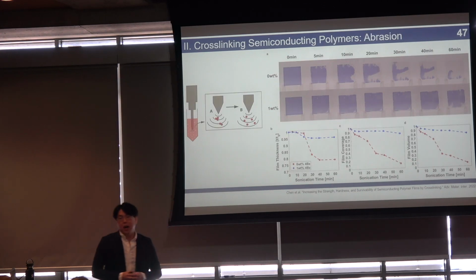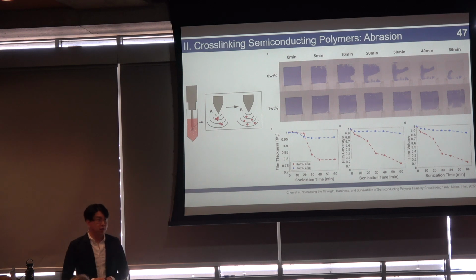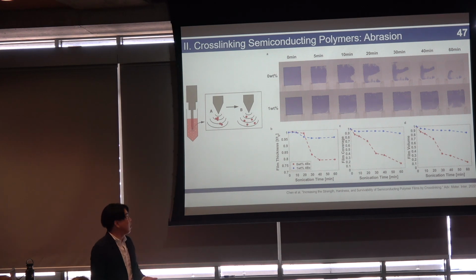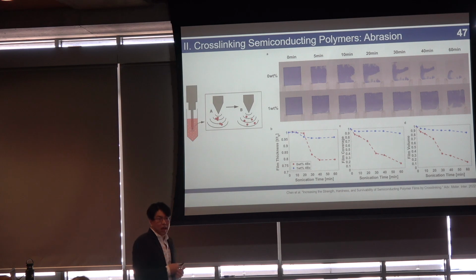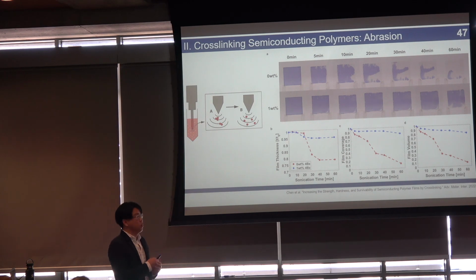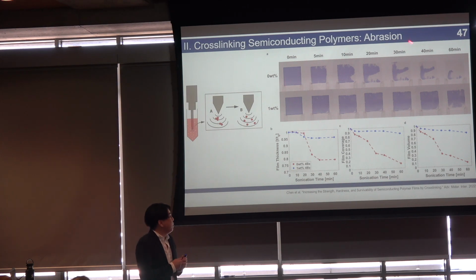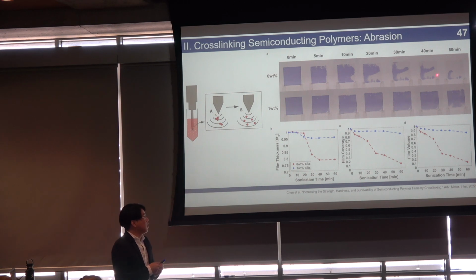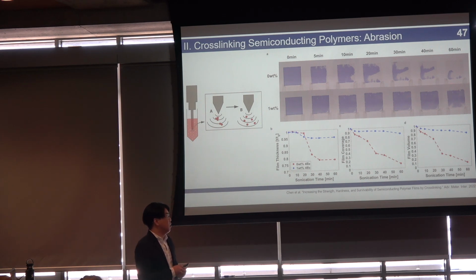And we can take a deeper dive into the abrasion resistance of our films, because that's one of the big things we cared about. So we could use a sonicator to actually abrade these films with sound waves, and we see that the non-cross-linked film over 60 minutes is basically abraded away, and the cross-linked film survives relatively well.